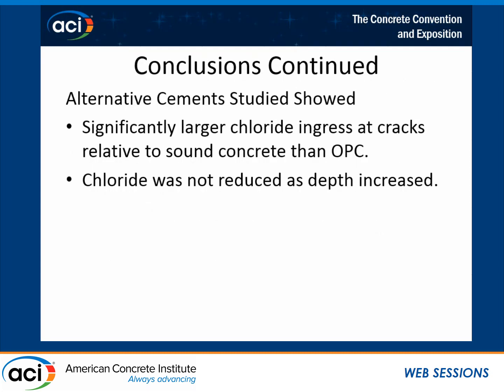Conclusions continue. The alternative cement studies showed significantly larger chloride ingress at cracks relative to sound concrete than OPC. Chloride was not reduced as depth increased, so that means they could go into corrosion faster. Matter of fact, on some of these we found not that much top bar corrosion. On a good portion, the bottom bar corrosion was about as high as the top bar corrosion.